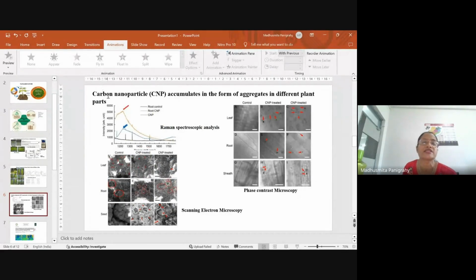We first checked that the carbon nanoparticle is taken up by the rice plant. We confirmed this by Raman spectroscopic analysis, taking different parts of the plant like root, stem, and sheath, and we saw that the raw carbon graphite powder wave number is matching those found in the samples. So we are confirmed that the carbon nanoparticle is taken up.